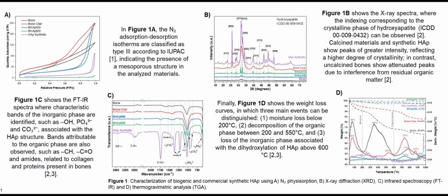Figure 1 shows the characterization of biogenic and commercial synthetic hydroxyapatites by nitrogen physisorption, X-ray diffraction, XRD, infrared spectroscopy, FTIR, and thermogravimetric analysis, TGA. Figure 1a, the nitrogen adsorption-desorption isotherms are classified as type IV according to IUPAC, indicating the presence of a mesoporous structure in the analyzed materials.